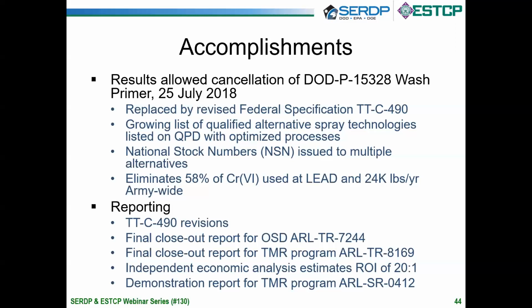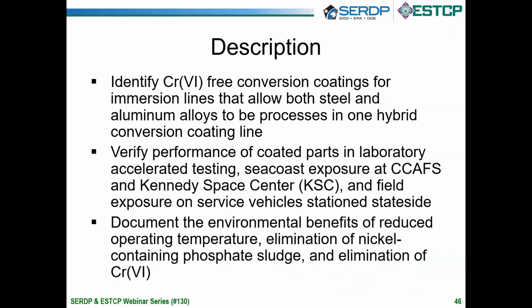So the next project is the zirconium-based pretreatments, conversion coating for aviation and ground support equipment. The goal here is to identify not just a hex chrome-free conversion coating, but a chrome-free conversion coating for immersion lines. What this does is, if you can treat steel and aluminum along the same line, you can consolidate the process on one line, run aluminum and steel through the line, and save a lot of space at the facility, which makes room for other processes such as e-coat or any other process that's important to that facility.